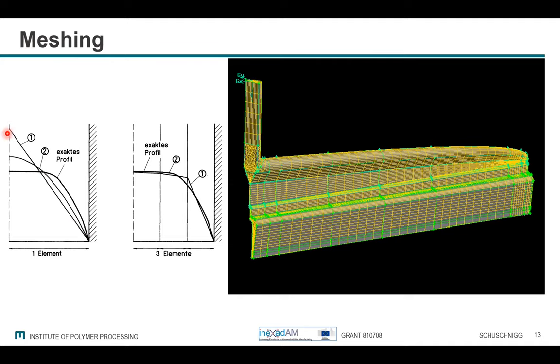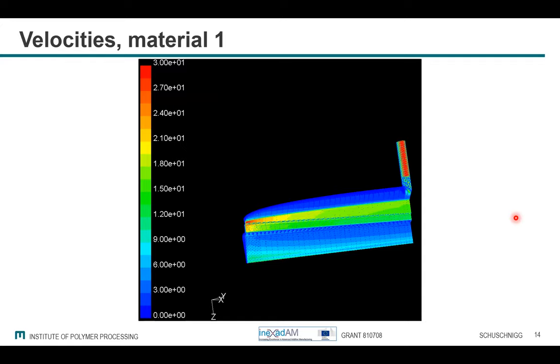One problem is, for example, if I have just one element over the height of the film die and I mesh it, I will get this velocity profile, with wall adhering at one side and maximum velocity in the middle and at the other wall adhering. Therefore, it would be two elements. Here is the middle section of the film die. This is the exact profile. So with three elements over one half width, it's going better. In this case, I say minimum 10 over the height of this die. Then I get out my velocities.